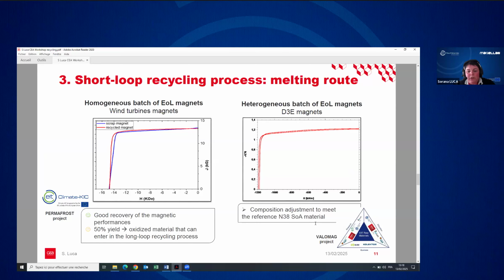So here are some examples of recycled magnets, the results obtained within different projects. In the first case, a homogeneous batch of end-of-life magnets coming from wind turbines was used to fabricate alloys, and after that magnets. We can see that we have a very good recovery of the magnetic performances of the starting material, using only the end-of-life magnets as the starting material to fabricate magnets. This project was financed by EIT Climate-KIC.